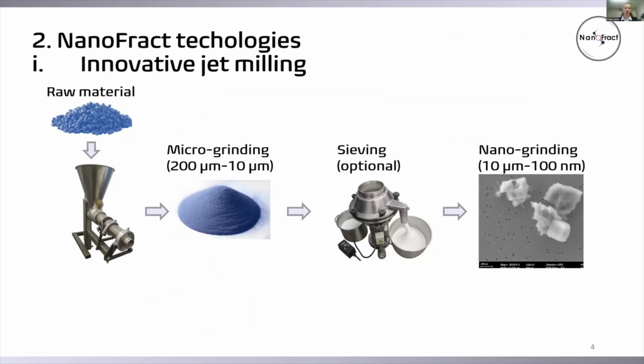Now I directly go to our innovative jet milling technology. Here you can see what our typical production line using this technology looks like. Usually we receive raw material as granules, usually polymers. They are inserted directly into the conveying chamber. After that, they reach the grinding chamber, where they are milled to a size from 200 down to 10 microns. After that, we optionally conduct sieving to obtain narrower particle size distributions. And at the last step, we repeat the grinding to obtain particles below 10 micrometers or at nanoscale.